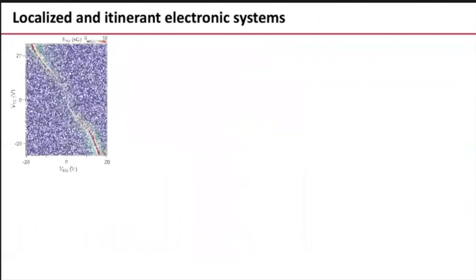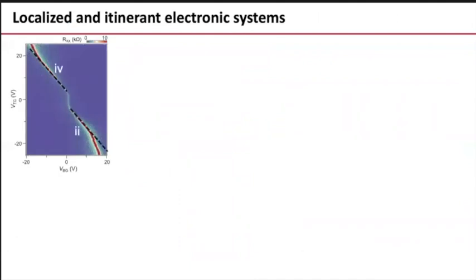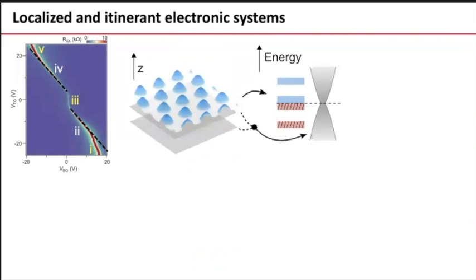So this system has these regions, which I call 2 and 4, where the behavior of the system is what you would expect, okay? This diagonal line with an angle given by the ratio of the capacitances. And it has these regions 1, 3, and 5, where it deviates, the most dramatic being region 3, where it's vertical, okay? The location of the charge neutrality point versus the dual gates. This system can be thought of as two systems. One system, which is related to the long wavelength Moiré pattern, where you have charge localized and you form equivalent Hubbard bands like structure, okay? And then the other system, which is related to the bottom interface, where your electrons are just bilayer graphene-like, okay?